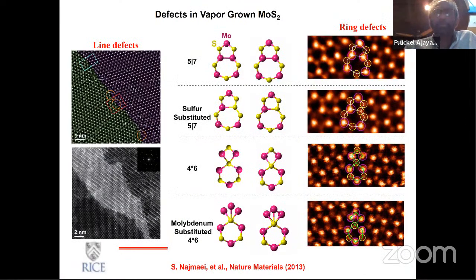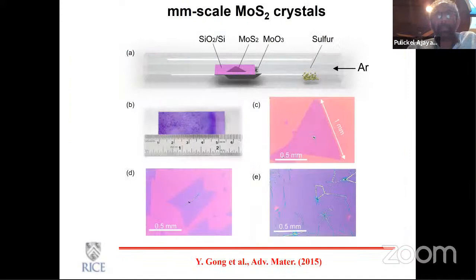Very similar thing with other structures like molybdenum sulfide. Of course, the grain boundary is a little bit more complicated than graphene because it's a two-component system, and you can have defects that relate to sulfur vacancies or metal vacancies. But in general, there have been predictions and experimental proof that these types of topological defects do exist in the grain boundaries of transition metal dichalcogenides as well.